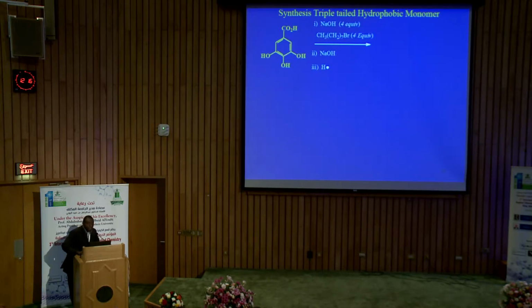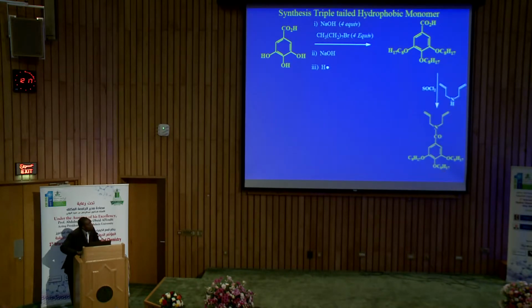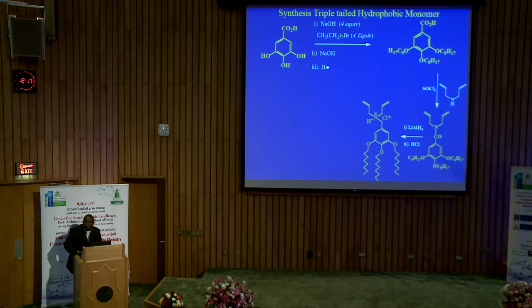For the triple tail, we start with gallic acid, which is treated with 4 mole equivalent of sodium hydroxide and bromo-octane, and then subsequently treated with sodium hydroxide and then hydrolyzed to get trioctyloxy benzoic acid, which is converted into acid chloride using thionyl chloride and subsequent reaction with diamine to give amide. The amide undergoes reduction followed by acid hydrolysis to form an amine, and then we protonate the amine so that it will be water soluble. So this is our monomer. All the compounds were isolated, purified, and characterized.